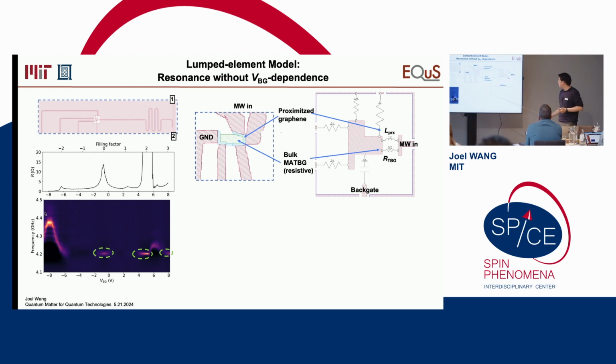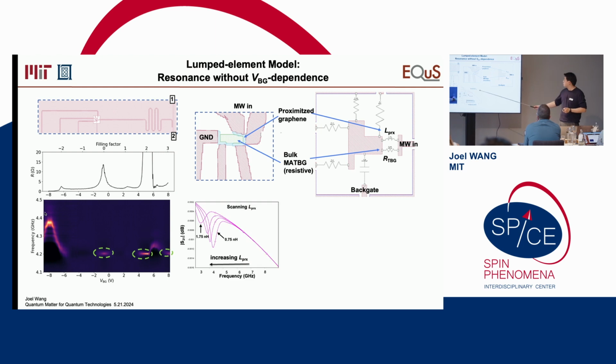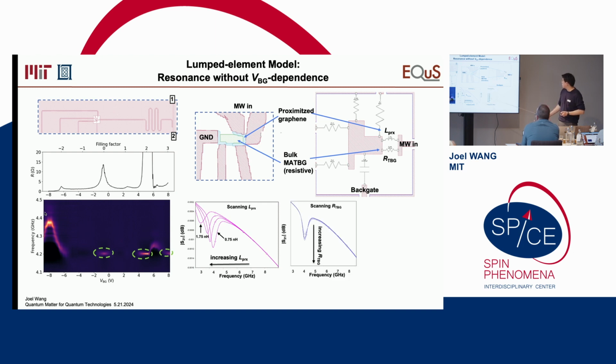And we can actually perform the microwave simulation and reproduce exactly the frequency of these devices as a function of the proximatized inductance. We also find that the change of the resistance doesn't shift the frequency at all, but it changes the quality factor of the resonator. This is something expected for a standard parallel LR resonator. You can see the more resistive it is, the higher the quality factor of the device or the resonance that we see. That is confirmed by this one.